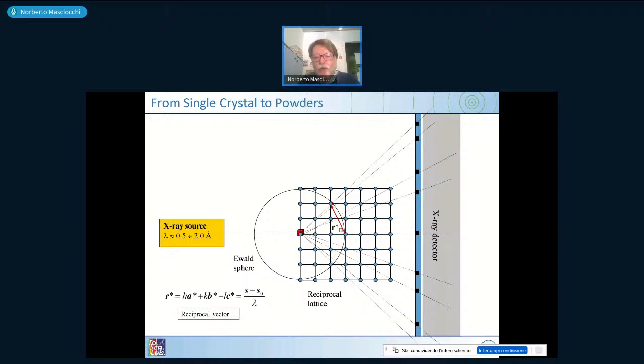So having all the points measured allows you to detect the symmetry of the system, the size of the unit cell, and the position of the atoms. To do this, you have to rotate the sample. Now we make a very bad experiment. You crush the single crystal into many, many tiny pieces. So basically, you obtain a powder of misoriented crystals.